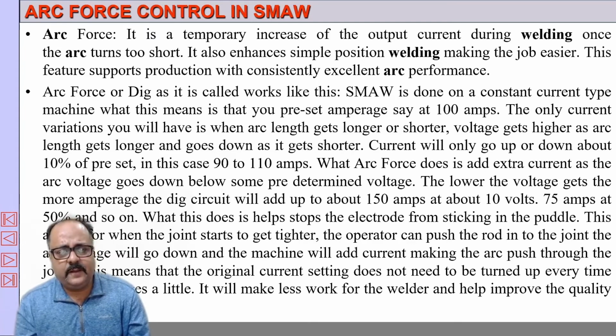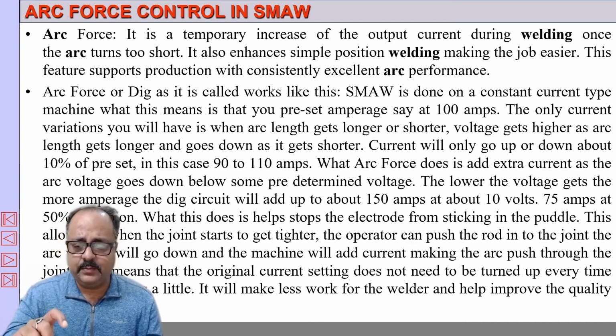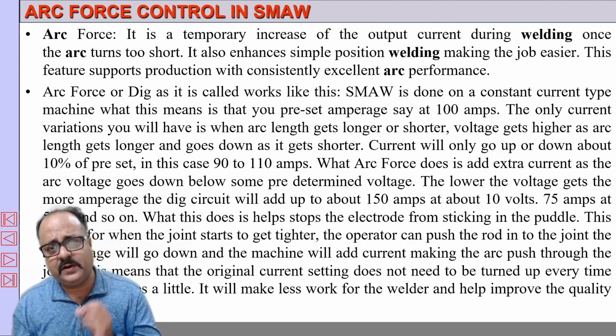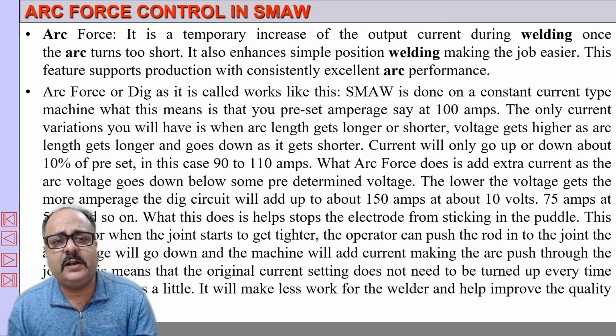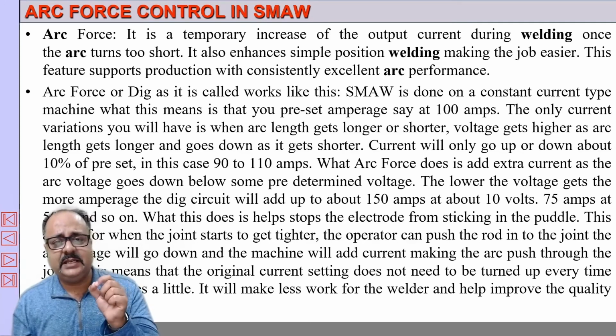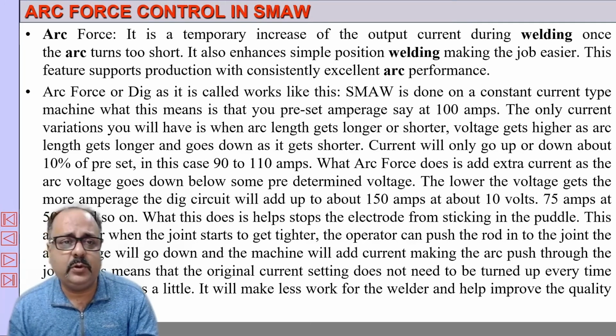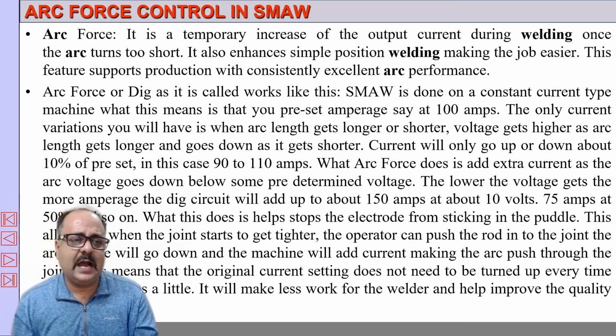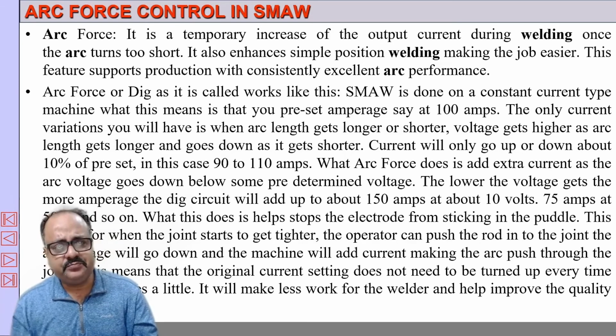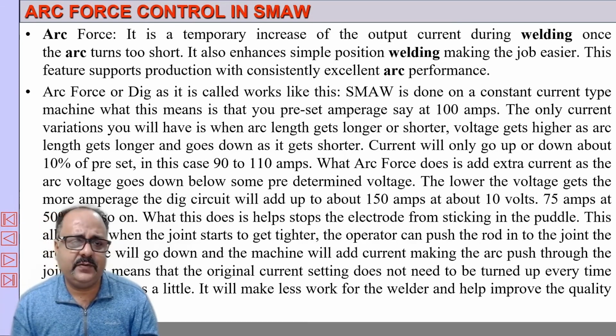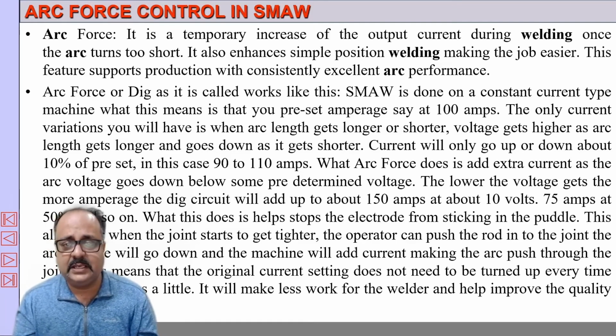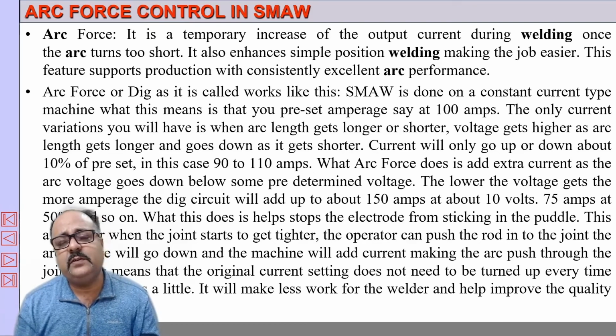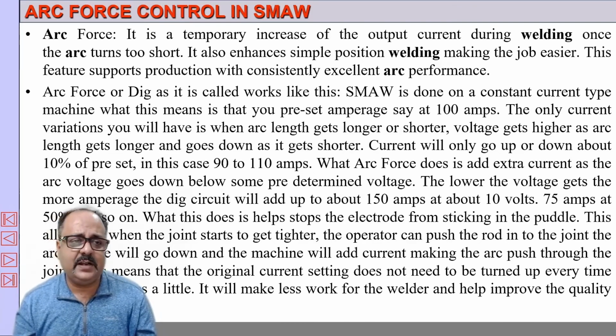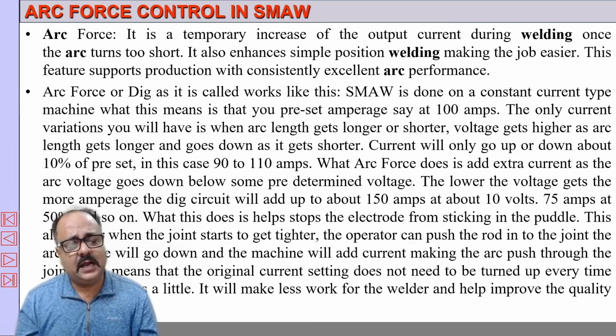So what happens? It temporarily increases the output current during welding once the arc becomes too short. So what happens when the arc becomes short? The voltage drops, and because of the voltage drop, sometimes there is a freezing of the weld pool. When this weld pool freezes, the stick or the rod may stick to the weld pool, and that condition is avoided by controlling the arc force, where temporarily the output current is increased when the arc becomes short, when the operator by mistake brings the electrode very close to the weld metal pool. So that feature is a very neat feature given in modern welding power sources, the arc force control.